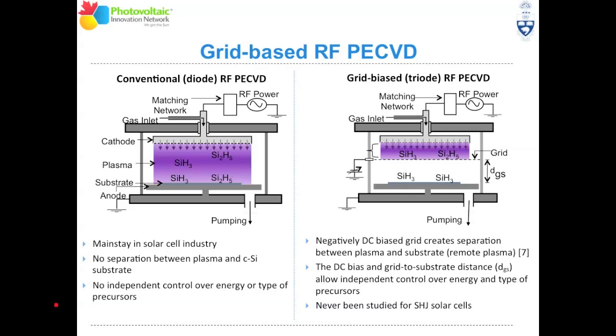This also plays a major role in terms of getting good hetero interface properties, because now you can modulate the energy of the precursors so they don't damage the crystalline silicon surface, and also you can have the appropriate precursor species to get really good hetero interface properties.